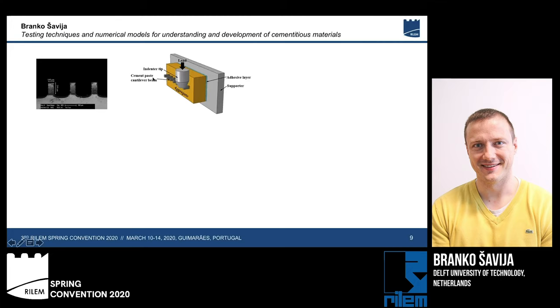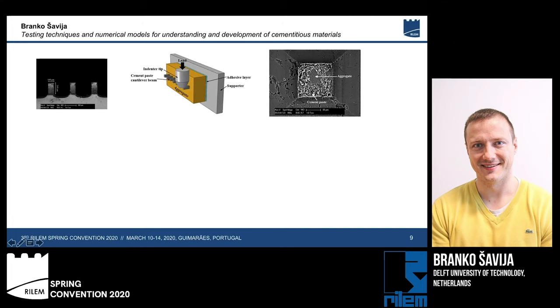And by applying bending loads, we can, again, fracture these materials. So this is an image of a fracture surface in an SEM, which is also tortuous. And then we have different pores that guide the fracture process.